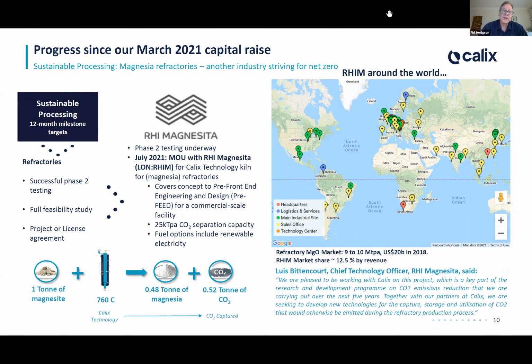In sustainable processing, we announced in July 2021, a tie-up with RHI Magnesita. RHI Magnesita is one of the largest, in fact, the largest refractory company in the world. Now, what is refractory? It's those little bricks that sit inside steel kilns, cement kilns, and those bricks actually protect and hold the heat in the process and protect the steel vessels. Now that refractory is made out of what's called magnesia, magnesium oxide, and that's made in much the same way as lime is made, which is calcium oxide.